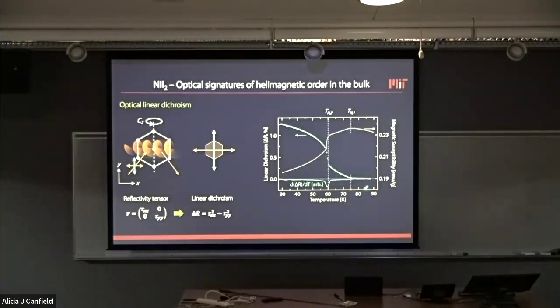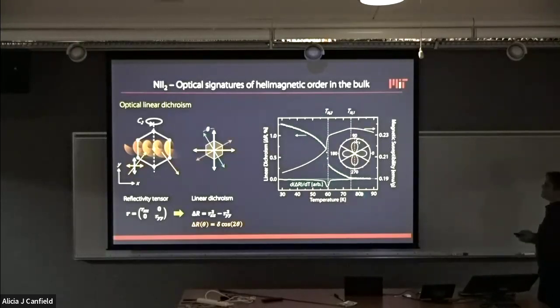There is another signature at the higher temperature transition to the first magnetic order, but I'm not going to discuss that in detail. But there's a sudden jump at 59 Kelvin with a rotational anisotropy pattern, which allows us to identify this twofold axis, C2.